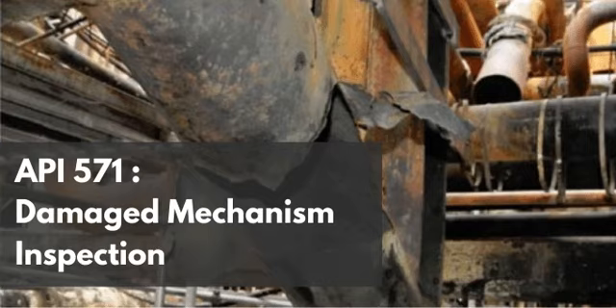And because the component is under mechanical tension, the underlying grain boundaries are constantly being exposed. The anodic dissolution, which is the actual dissolving of the iron matrix into the electrolyte, concentrates precisely at those exposed grain boundaries. And that concentrated dissolution is what dictates the morphology of the damage, right? Exactly. ACSCC is strictly intergranular.